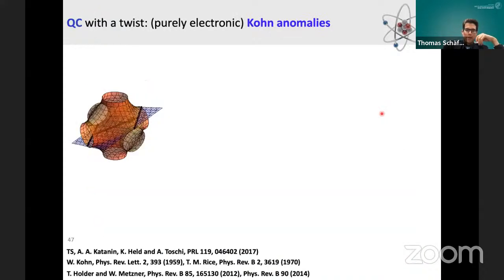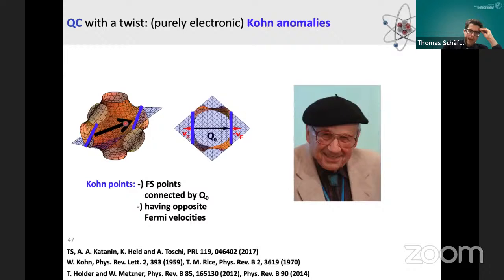Well, we took pen and paper again and went a step back, namely, we analyzed the so-called Fermi surface of this object. The Fermi surface separates the unoccupied from the occupied region of, let's say, my band structure. What you see here is the Fermi surface now in 3 dimensions. We have certain pairs of lines in this Fermi surface, which are lines of so-called Kohn points. These Kohn points have the property that they connect large parts of the Fermi surface by a momentum vector q and having opposite Fermi velocities.